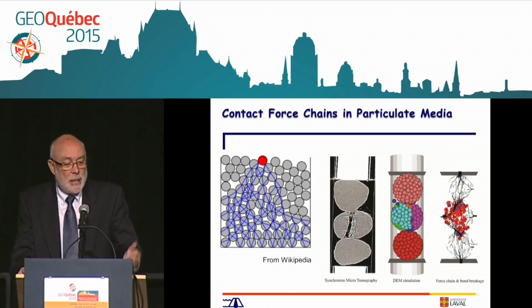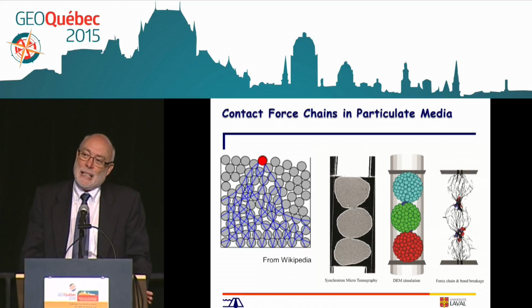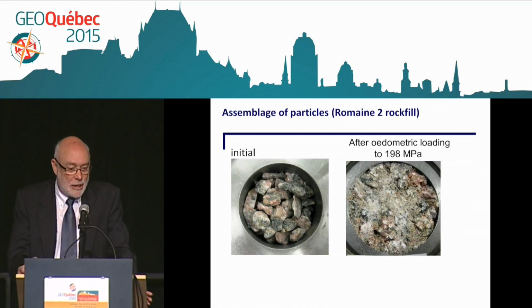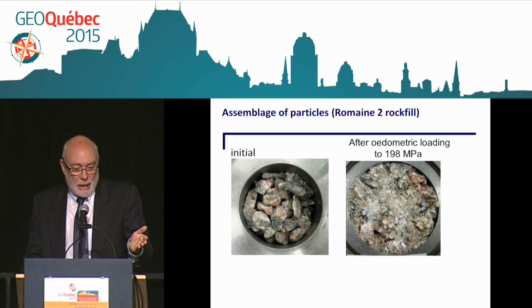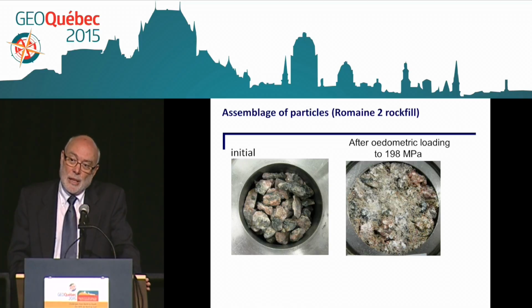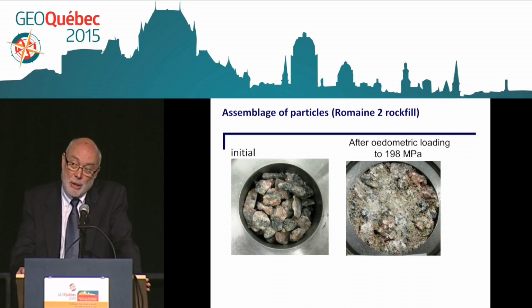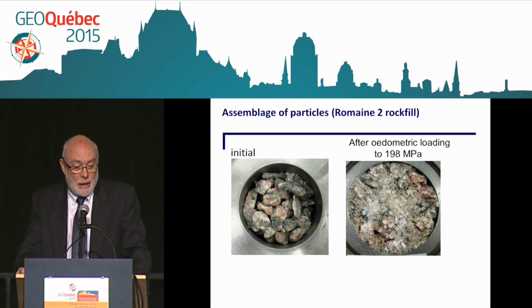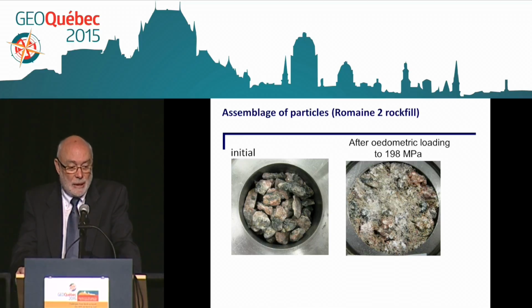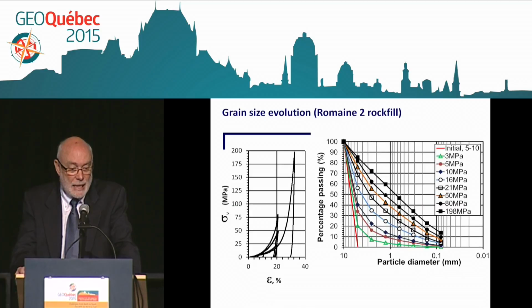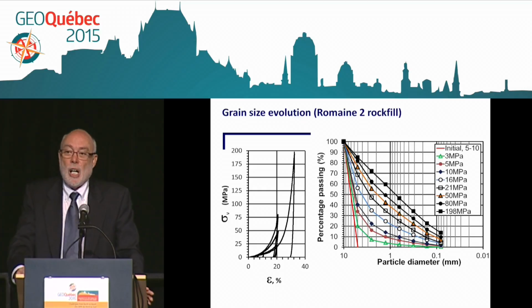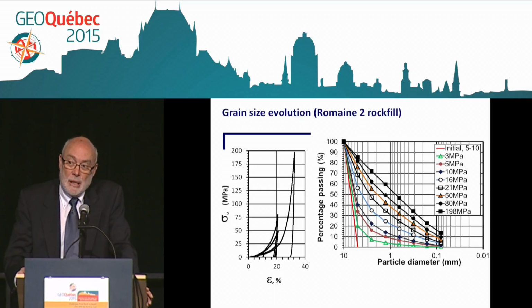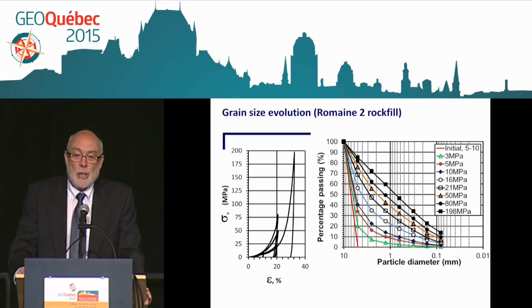We can see, now this is a bit excessive, that the particle will not crush like a glass, but it will actually split and change its grain size. For Romaine 2 in an oedometric cell, initially we took a fairly uniform material, 5-10 millimeters. And after oedometric loading to about 200 megapascal, we have crushed, or fragmented, the material to much smaller sizes. This is illustrated here on this relationship of grain size, the initial distribution in red, and progressively it moves to what I call the ultimate grain size distribution, where it becomes more or less stable with further loading.